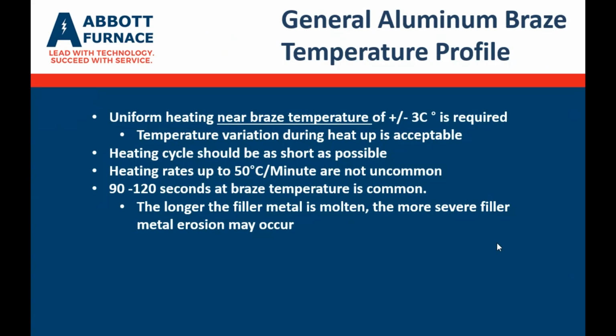Obviously, the heating cycle should be as short as possible, one from a production standpoint and two from a utility standpoint. Heating rates up to about 50 degrees C. I think the last slide we saw was 45 degrees C, but those kind of heating rates are not uncommon. Generally, you're about a minute to 2 minutes at brazing temperature, which is enough to melt that liquid filler to form your joint.